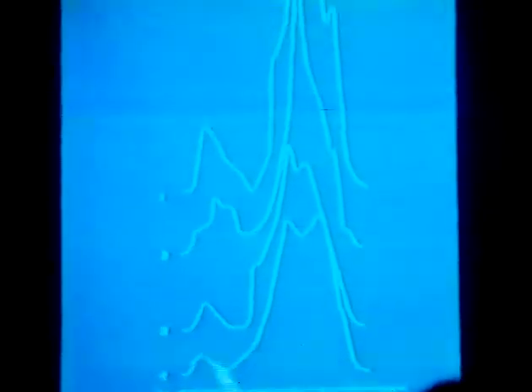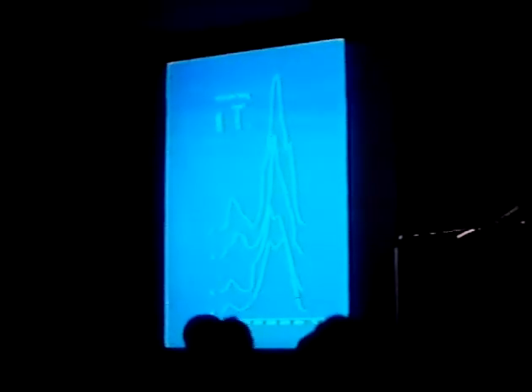In the case of rhodium, this mode of CO adsorption was investigated by temperature programmed desorption. In this spectra that you see in the slide, the dopant concentration increases from bottom to top. Two important characteristic alterations are obvious here.